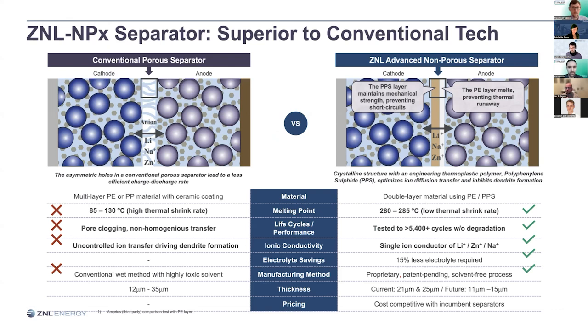We also have PE layers on the anode side. If you have a thermal event, that will shrink, but the integrity of the separator will hold because of the high melting point and low shrinkage of the PPS. You don't expose the electrodes. What happens in a conventional separator when there's a temperature event is that it will melt and you expose the electrodes.